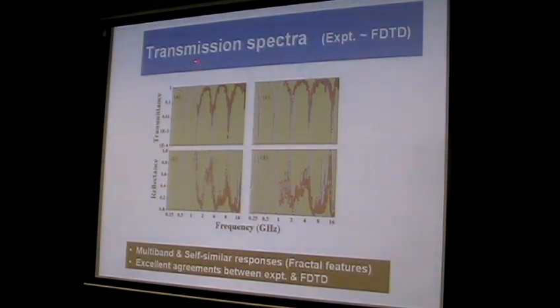So we performed an experiment to measure the transmission and reflection spectra of the fractal plate. Surprisingly, we found that there are several bands inside which the transmittance is strongly attenuated, which resembles very much the concept of photonic bandgap materials. And even more surprisingly, we found that in between these two band gaps, there is always a frequency regime where the transmittance is almost equal to 1.